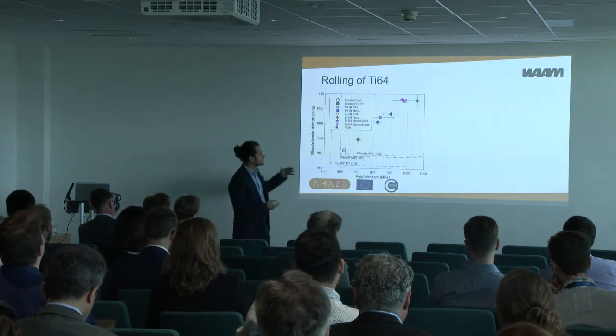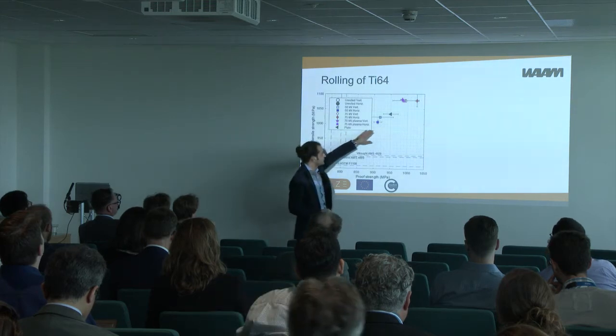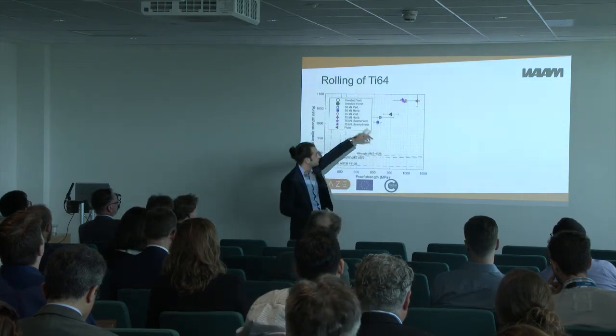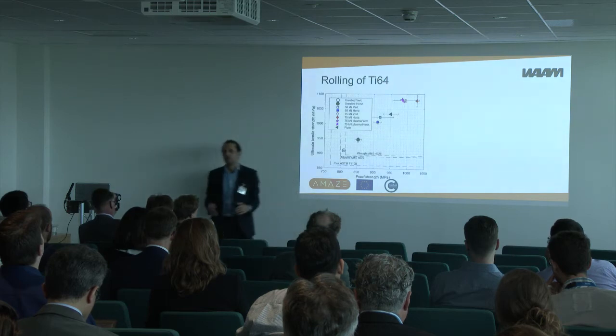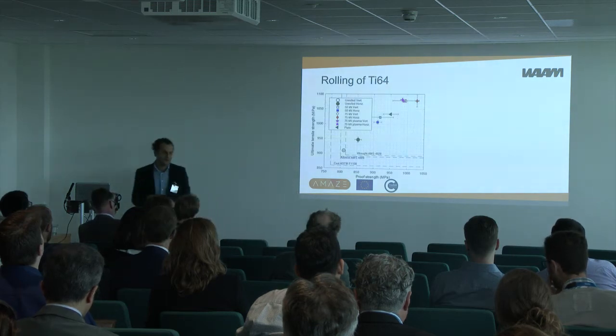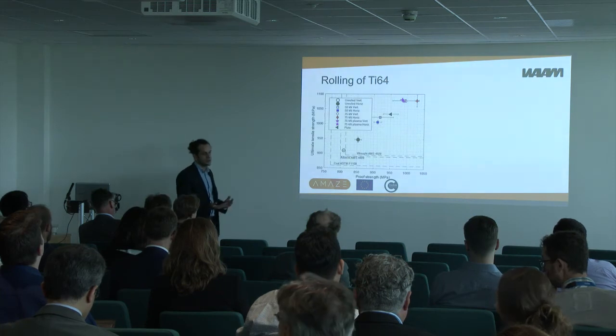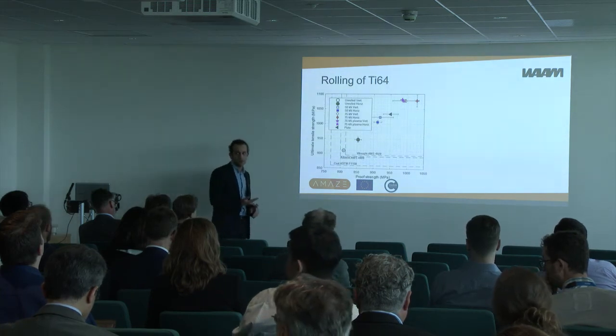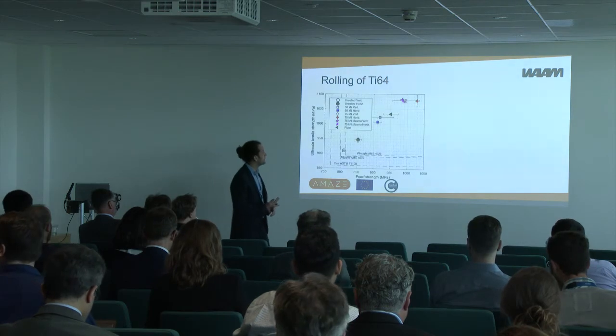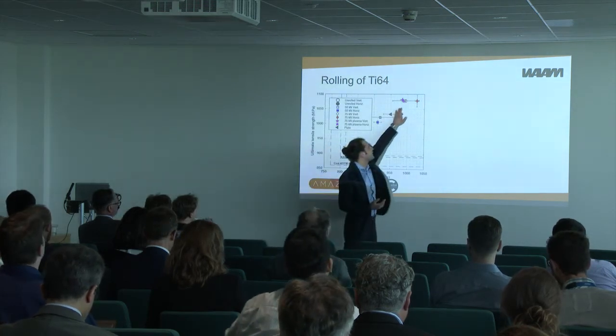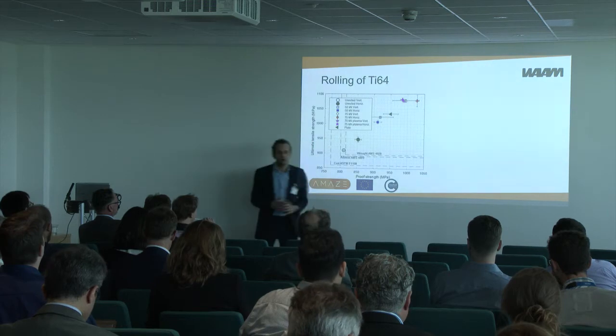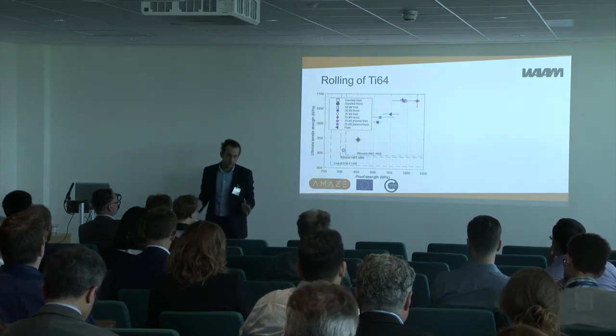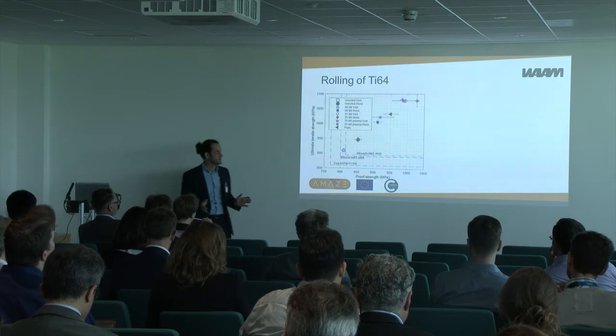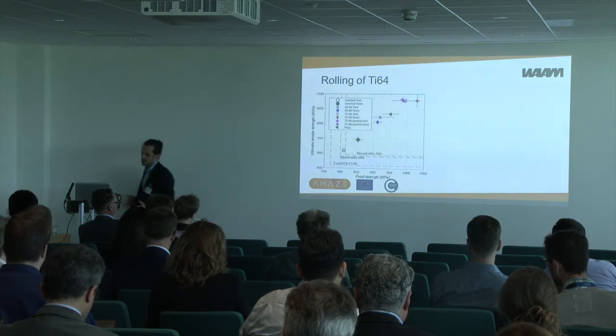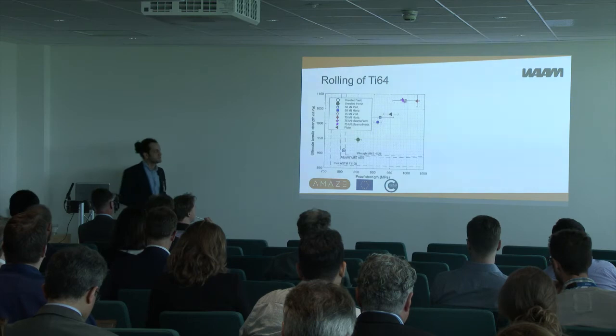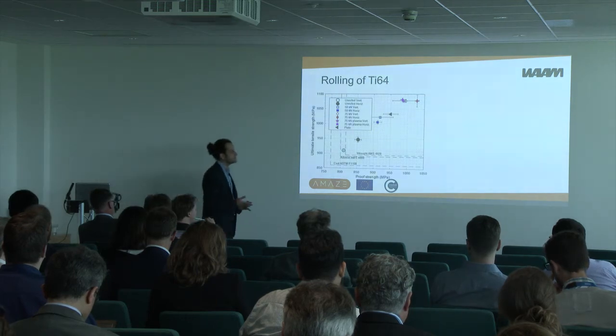The very good news is that as we introduce rolling, this difference is reduced, and then finally for a rolling load of 75 kilonewton, we are producing parts that have got properties that are even better than what's flying today. So we could argue that we can make parts that are cheaper, we can make them faster, and we can also make them lighter. I'm giving you two different data sets for 75 kilonewton because those parts were made on two different machines by two different operators with two different power sources, and they were tested in different places. And it just goes to show that we can produce consistent properties also thanks to this addition.